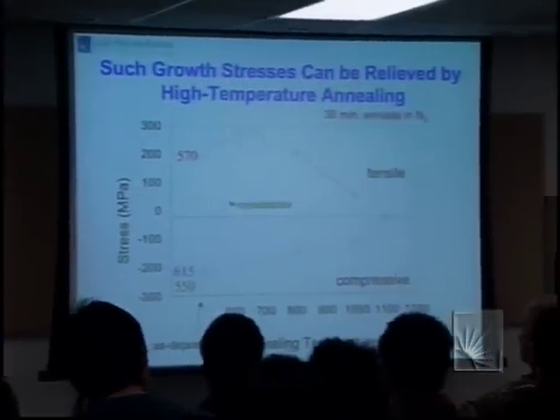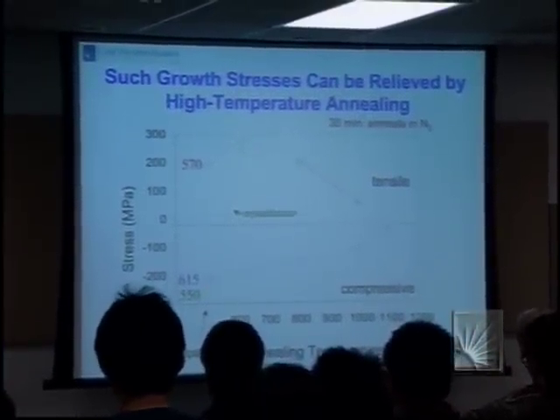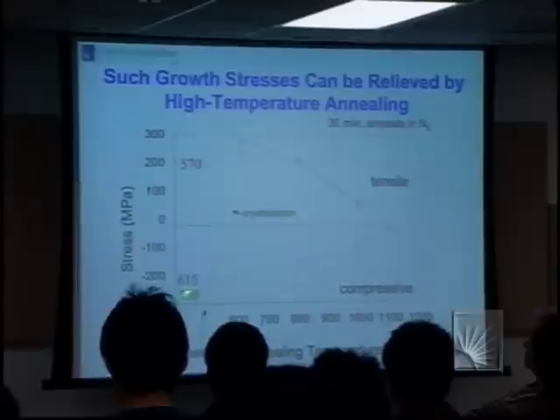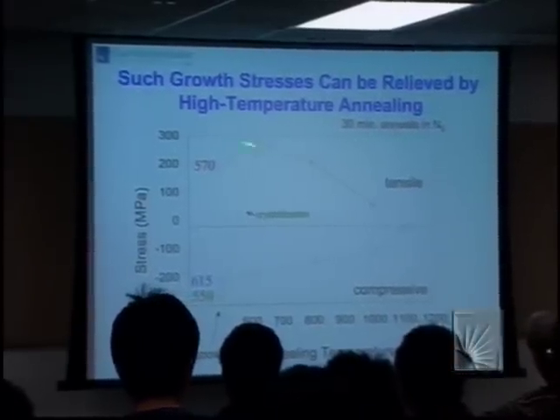These are conventional types of annealing processes where there's enough mass transport going on to allow these residual stresses to be relieved. The 550 material, when you heat it at 615, it all crystallizes, so it goes from a large compressive stress to a large tensile stress, and then it too begins to anneal. So what's the big deal?